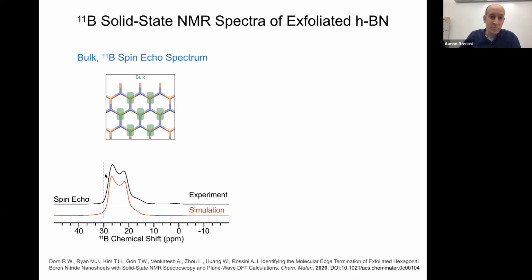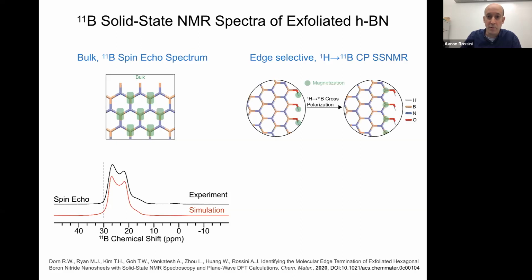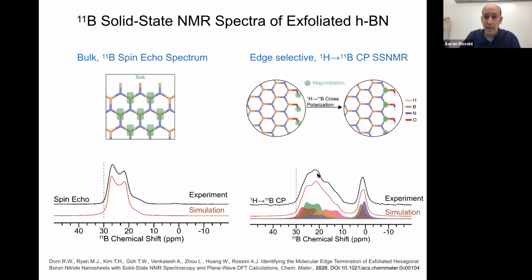And this matches what's been reported for boron nitride. The isotropic chemical shift is at about 30 ppm. That also matches the literature results. Okay, if we want to see the edges, we can just do a proton to boron cross-polarization experiment. This is done at room temperature because protons offer good NMR sensitivity. And so when we look at the cross-polarization spectrum, we can now see some new signals coming in.